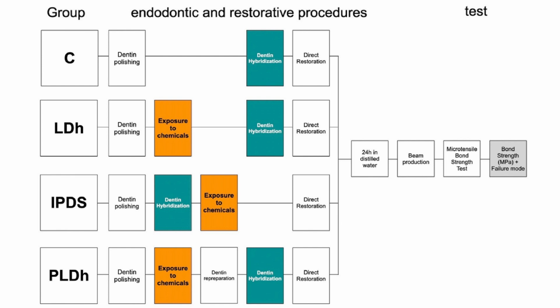They had 20 recently extracted, caries-free third molars collected from patients between 18 and 35 years of age. Teeth were mounted on acrylic plates and were divided into 4 groups using randomization software to reach 5 teeth per group. In the IPDS group, the specimens were submitted to dentin hybridization before the exposure to endodontic chemical substances. In the LDH group, dentin hybridization occurred after simulating the endodontic treatment, at the time of final restoration. In the PLDh group, the dentin hybridization occurred after simulating the endodontic treatment and after the repreparation of the dentin with a diamond-coated ultrasonic tip.